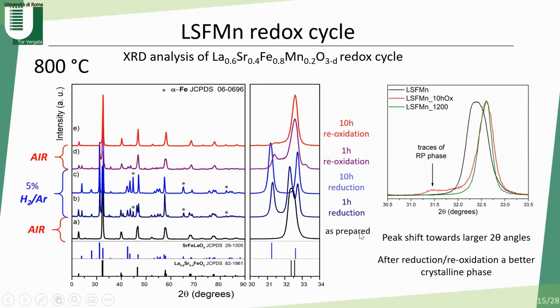As we can see from as-prepared to after 10-hour reduction, here there is the enlargement of the main peak, where a single peak is perovskite, a double peak is Ruddlesden-Popper structure. We see that after 10 hours the reduction is complete, but just after 1 hour of reduction we can see iron exsolution. Moreover, we have many other peaks that can be attributed to a metastable phase, which is manganese oxide, that is absent in both the as-prepared and end of reduction XRD patterns.